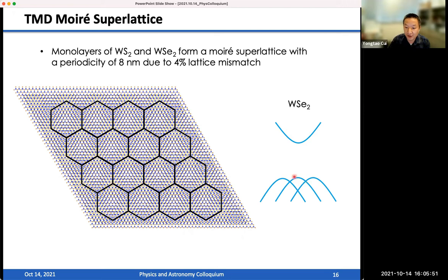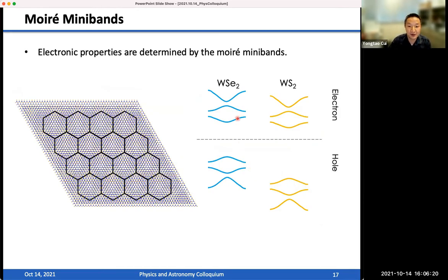It is then going to create overlap in the so-called mini Brillouin zone. At these crossing points, the crossing is avoided so that a gap opens at every one of them. That eventually makes the so-called Moiré mini bands. Originally we have one band, and if you fold this band, you actually get three bands. If you notice, this first band becomes much flatter compared to the original band. That's the case for basically all the energy bands involved in the system.